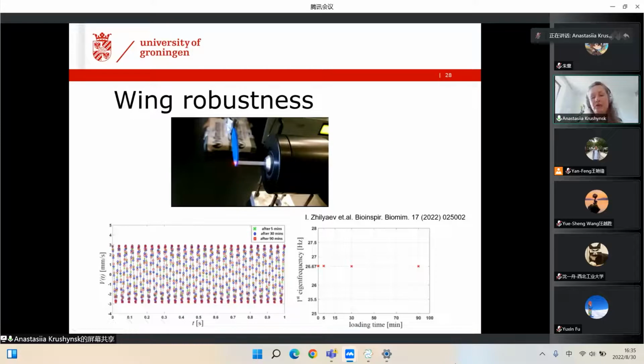The idea was that if there is a damage within the wing, then the eigenfrequency will change its value. But as you can see, even after 90 minutes of excitation, the eigenfrequency value is preserved. That means that there are no essential internal or external damages in the wing, and in total, the excitation time